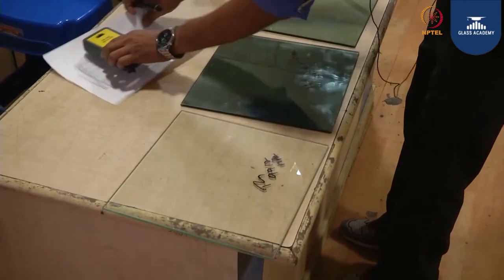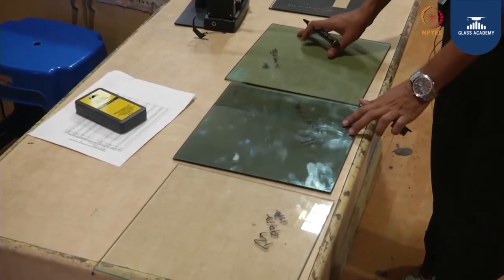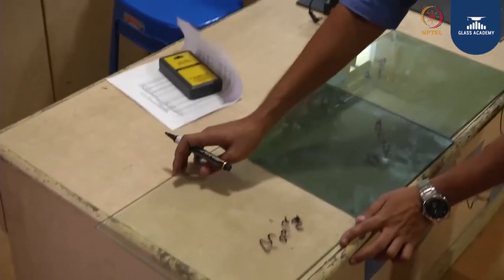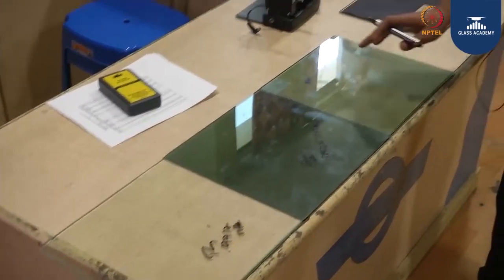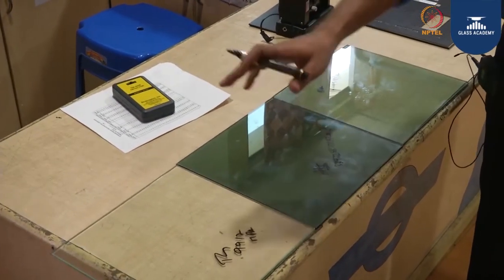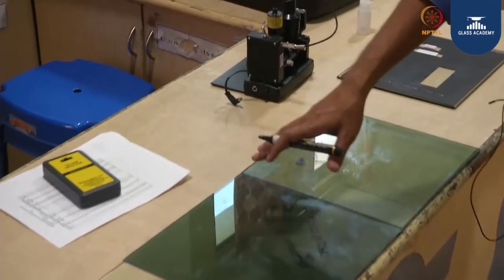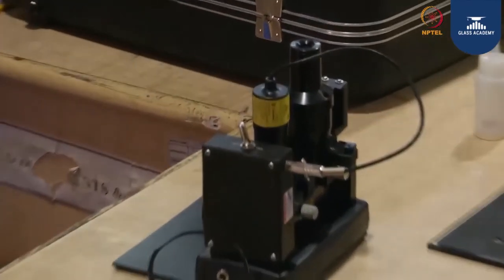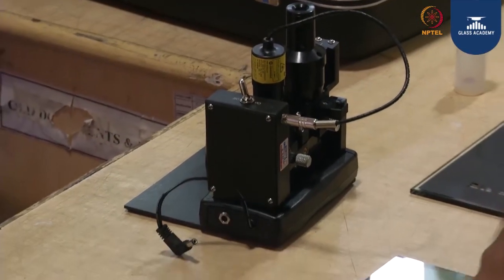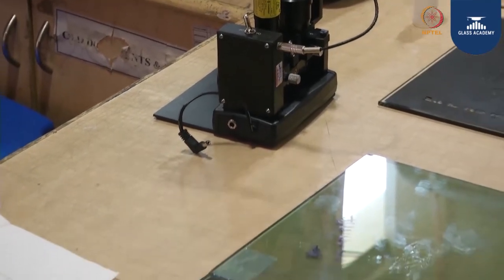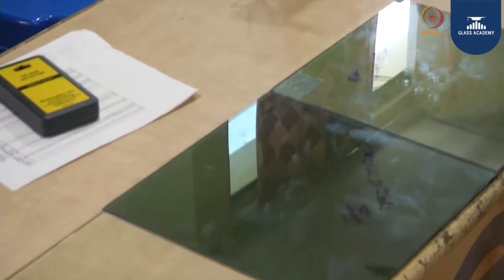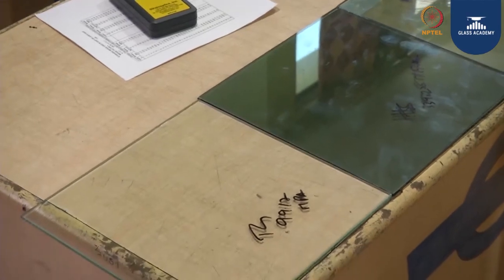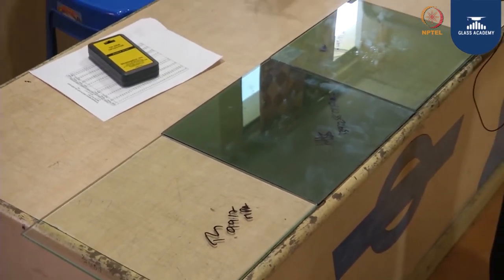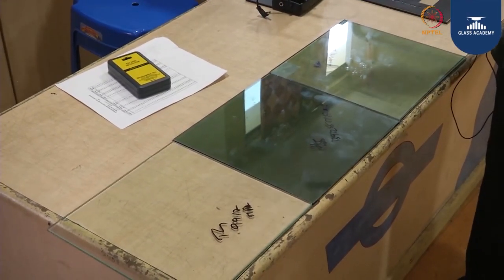So, now to summarize, when you see an annealed glass, HS glass and a toughened glass, by looking at the glass we cannot say which one is HS, which one is annealed, which one is toughened. We have two methods to differentiate. One is a destructive method, that is the fragmentation test. With the help of the breakage pattern and the fragments we will say whether it is an annealed, HS or toughened glass.